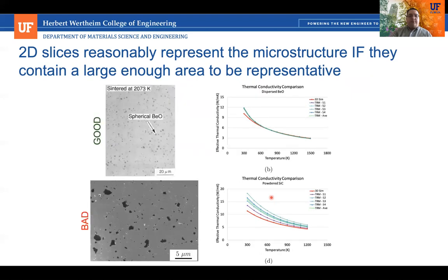And we could actually get a good reason of why that is. And in this case, here's a microstructure where it performed very well. There's very little scatter between 2D slices, and it compared very closely to the 3D simulation. We have a lot of particles, including big and small particles. Now, when we look at this microstructure which performed poorly, we do not have very many of these large particles. So there's not enough to get a good statistical description of these large particles. And because of that, we don't have a good statistical representation of this microstructure.